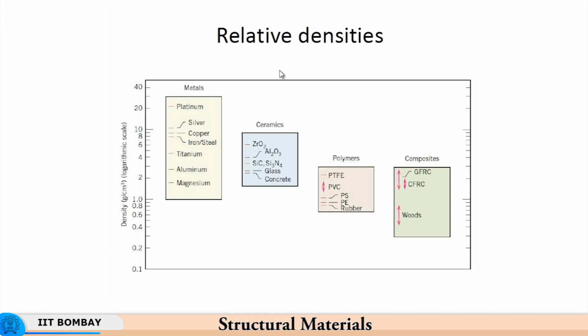Now, we come to the relative densities, because density is a very important parameter when it comes to deformation. Higher is the density, usually higher is the melting point, and therefore, the capability to remain undeformed at high temperatures is much better when we have materials with increasing density. For example, magnesium is a very lightweight material with a density of less than 2 gram per cc. Magnesium has a very low melting point.